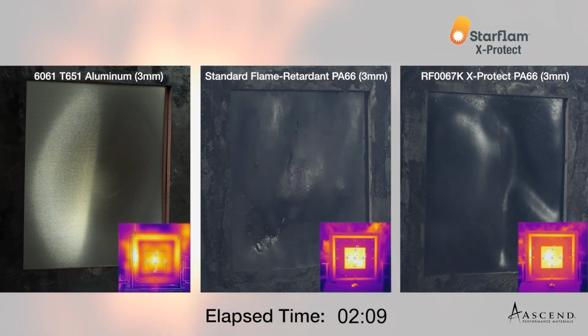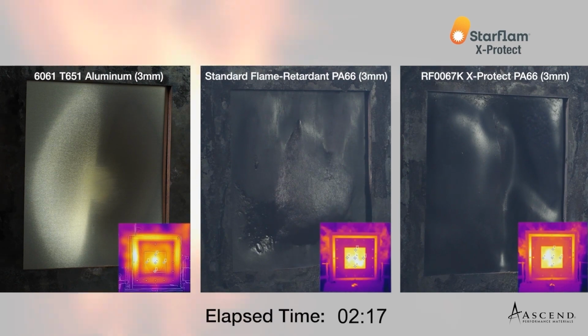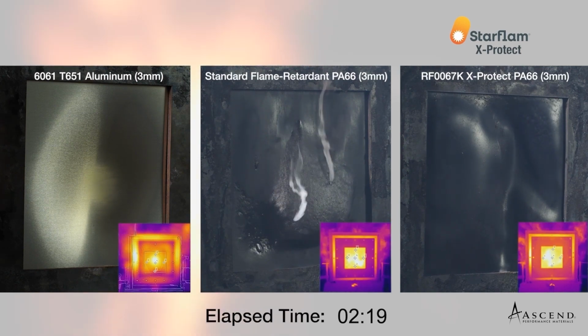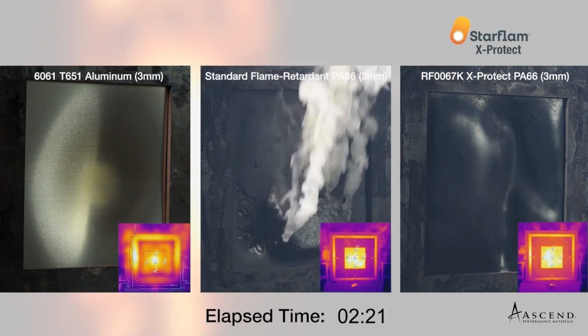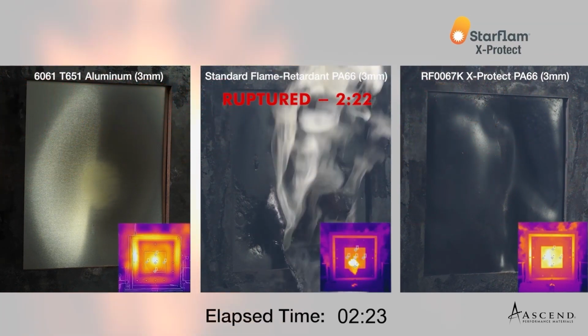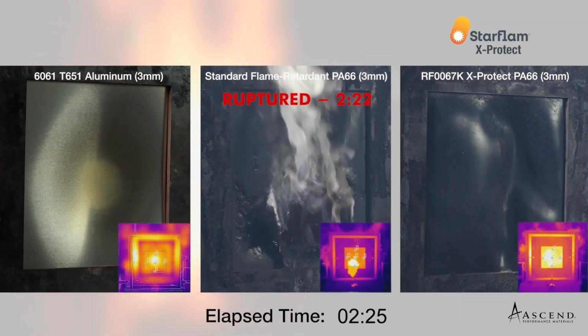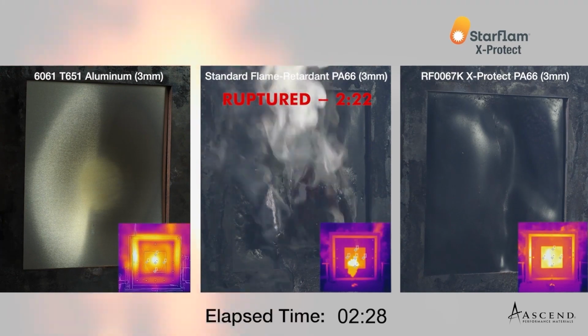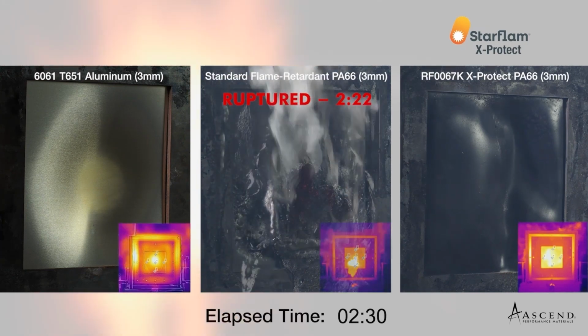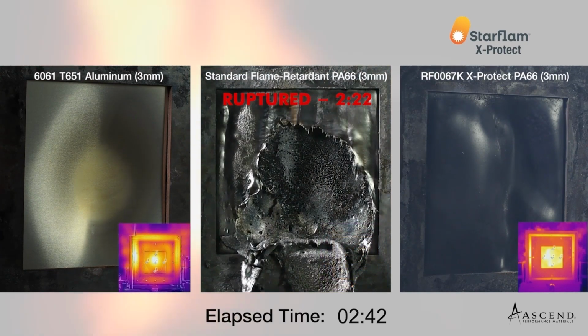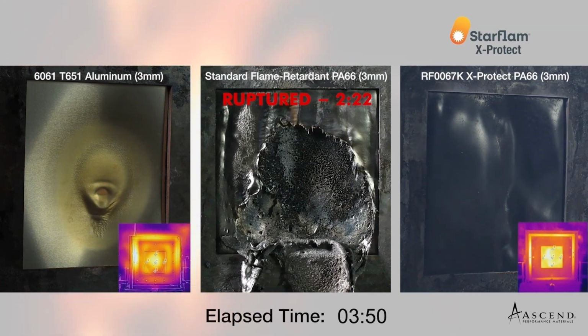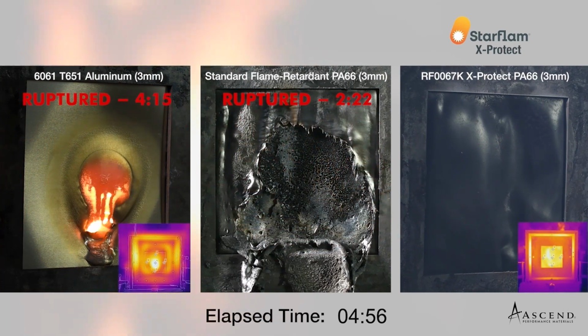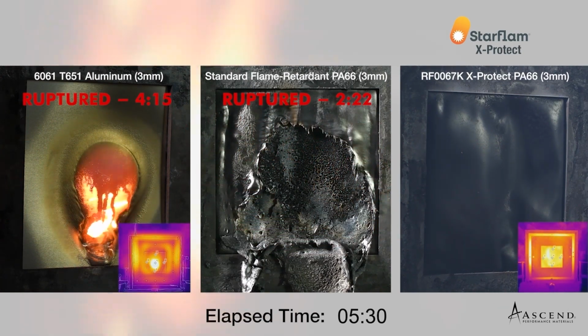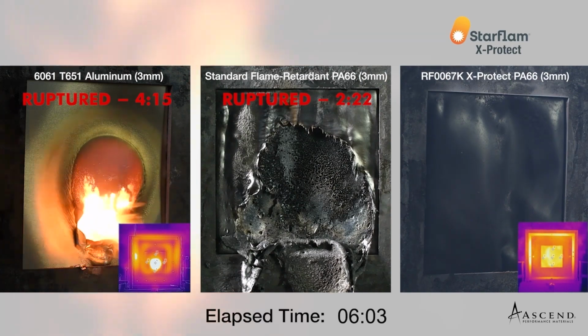So in the beginning, we see a little bit of buckling on the thermoplastic parts due to thermal elongation. But then the next development that we observe is a melting of the regular PA66 and the rupture of the plaque within 2 minutes, 20 seconds roughly. The same is happening to the aluminum plaque, just a little later. We have higher melting point, more heat capacity. So we need a little more time at that thermal power to heat through the aluminum, but we are able to rupture this within 4 minutes.